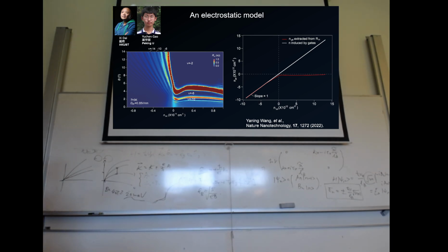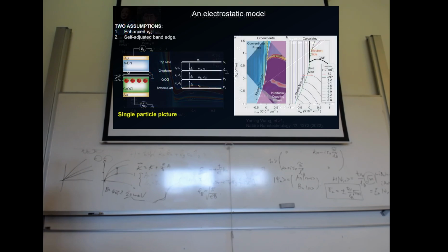And then there is a mismatch. For example, if you subtract this white line from this red line, you will get some missing electrons going somewhere, right? And the value is about 10 times 10 to the 12th, which is 1 times 10 to the 13th. It's quite a high carrier density. All this carrier density didn't go to graphene. They have to go somewhere. That's our first hypothesis.